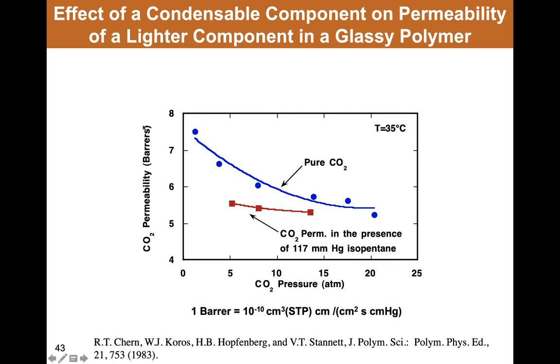So for example, this is showing CO2 permeability as a function of pressure in a glassy polymer. The pure CO2 permeability decreases with pressure, as shown here, but with just a low level of a second component, in this case isopentane, the permeation of the CO2 is actually suppressed. And so putting low levels of highly condensable penetrants that fill the Langmuir sites in a polymer can actually depress the permeability of lighter gases like CO2.